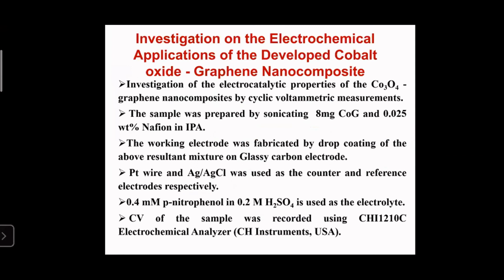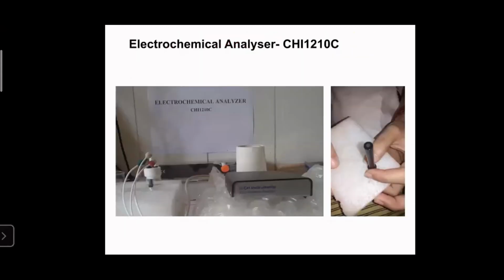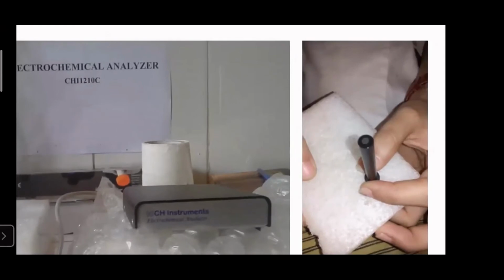And we have investigated the electrochemical application of the developed cobalt oxide graphene nanocomposites in the electrocatalysis of 4-nitrophenol. A modified glassy carbon electrode is used for the studies, and platinum wire is the counter electrode, and Ag/AgCl is the reference electrode. We have investigated the electrocatalysis of 4-nitrophenol in 0.2 molar sulfuric acid. Here I would like to show you, we got a very uniform layer of cobalt oxide graphene nanocomposite over the glassy carbon electrode.